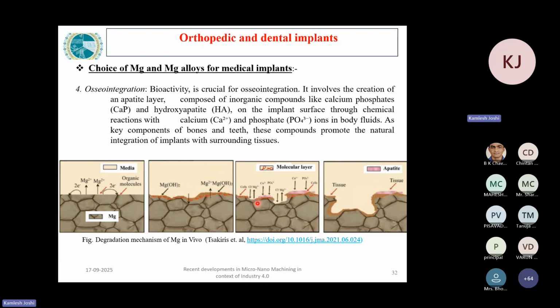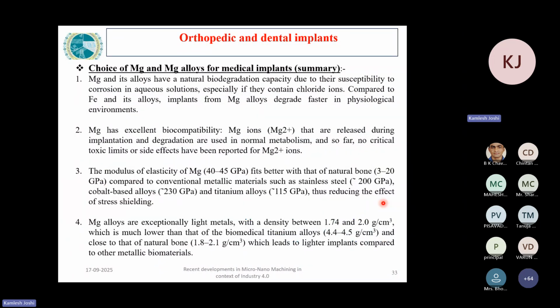This apatite layer, which can be seen here in the brown color, covers the part which is our implant, and tissue growth can happen over this. So this is a type of passive layer which stops the further degradation of the magnesium alloy implant, and it helps in the production of the tissue over the material.